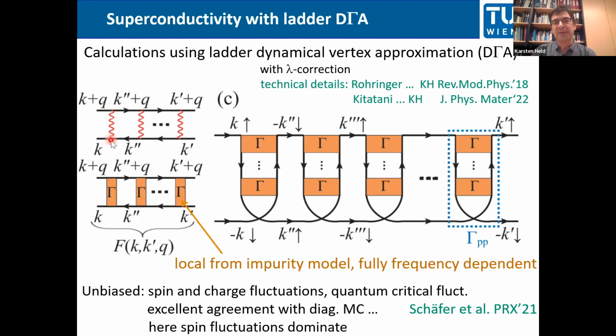In D gamma A, instead of this bare Coulomb interaction, we take a local vertex, with full frequency dependence, which we calculate from an impurity model. So it is similar to DMFT susceptibility calculations, except that you can do it self-consistently or in a Parquet approximation or with the lambda corrections, then you get corrections to these antiferromagnetic spin fluctuations of DMFT. And antiferromagnetism comes out much better. So there is actually a very nice paper of Thomas and Antoine, which compares various methods, including the D gamma A with also numerical methods like Monte Carlo simulations. And the agreement is really very good for the antiferromagnetic spin fluctuations.